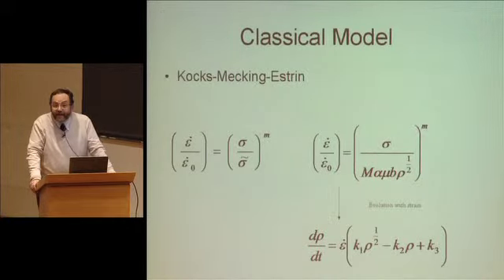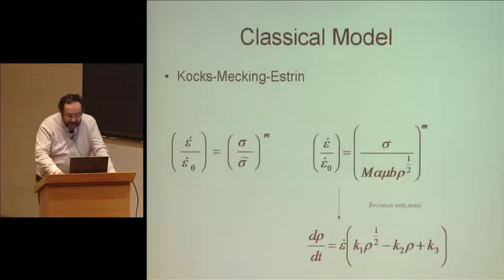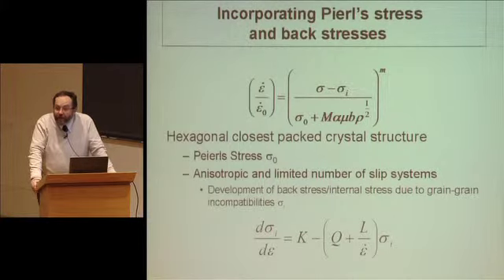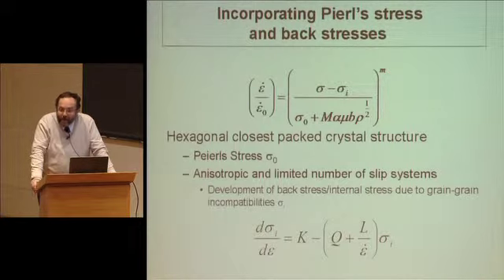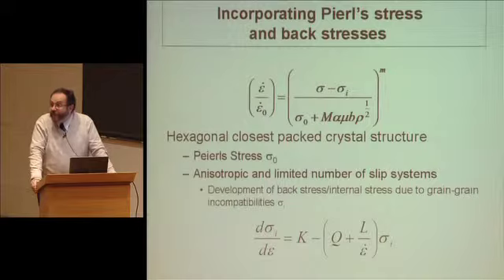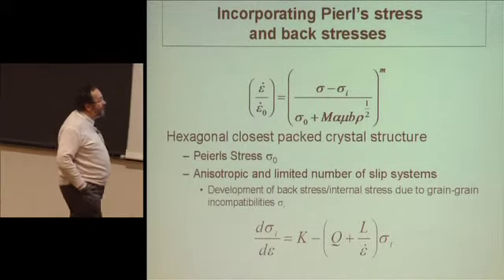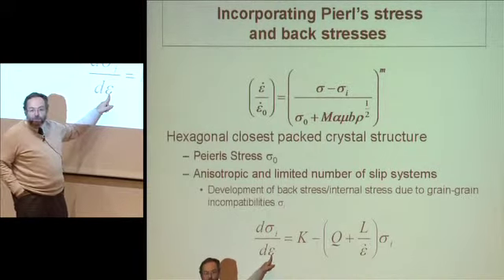So I'm going to show you how you can try to do that. This is model 0, the Kocks-Mecking-Estrin model. The 0.5 model is to see that the dislocation does not see that constraint. It sees the constraint minus the internal constraint, and the obstacle it needs to cross is not just a dislocation. There's also network friction. So what you're going to see when you see that, this is what was done on zircaloy alloys, is that the internal constraint is not just an incompatibility constraint. You're actually building incompatibility, but it is itself relaxing, slackening, with kinetics that are not necessarily the same as those that are connected to deformation speed or the movement of dislocations. So what you have here is a formulation of this internal constraint relaxation.